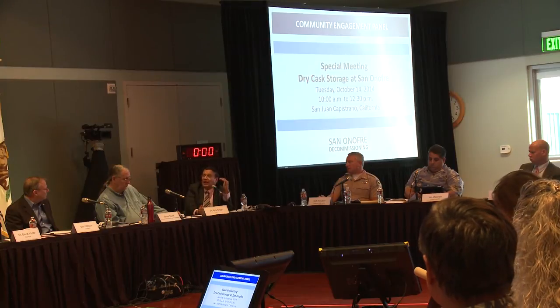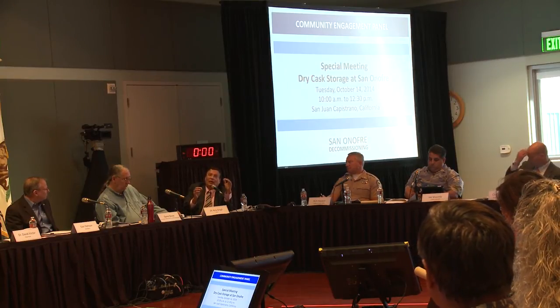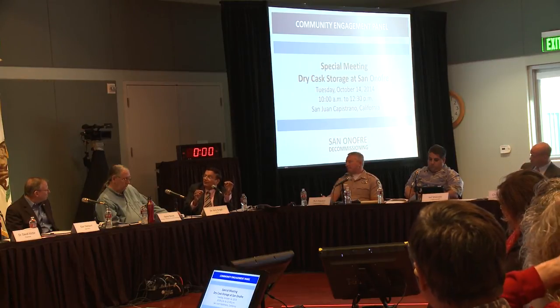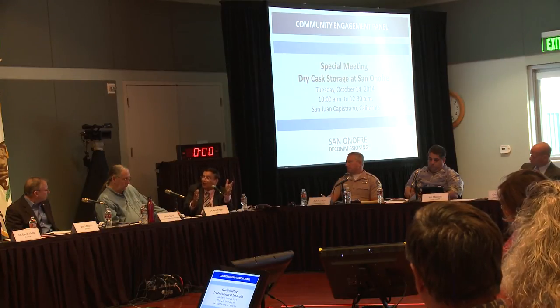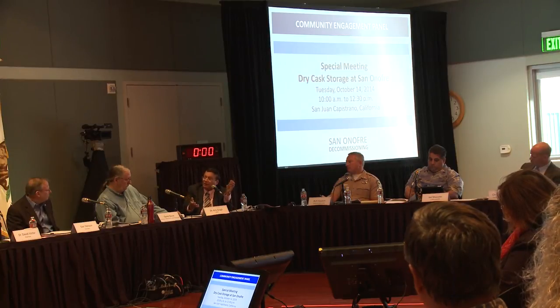So as our canisters get older, we are advising to, in a calibrated way, close the inlet vent. A small calculated amount, so your canister always stays warm. And if you do that, we expect that the rate of deposition will be significantly reduced.